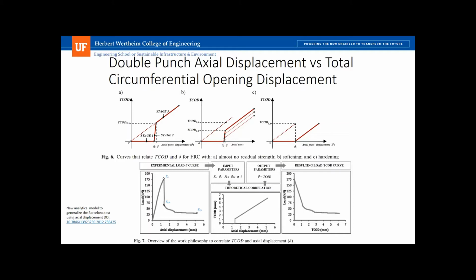In ductile materials like UHPC, however, you don't get that big jump in displacement when a crack starts to form. These cracks form more gradually, and so you get basically an axial displacement with zero circumferential increase until a certain point where you start to get micro cracking, and then you get this linear relationship. So we have a very nice linear relationship in ductile materials like UHPC after you get the first crack to form. So this is very handy.